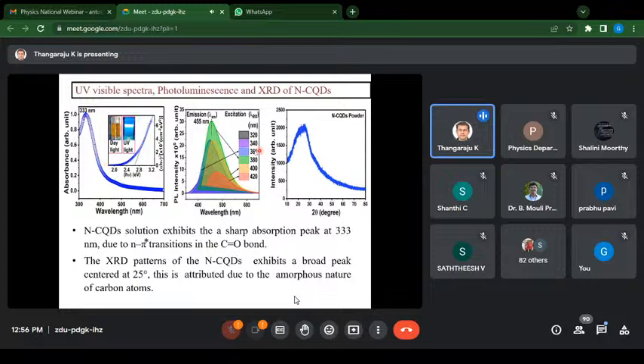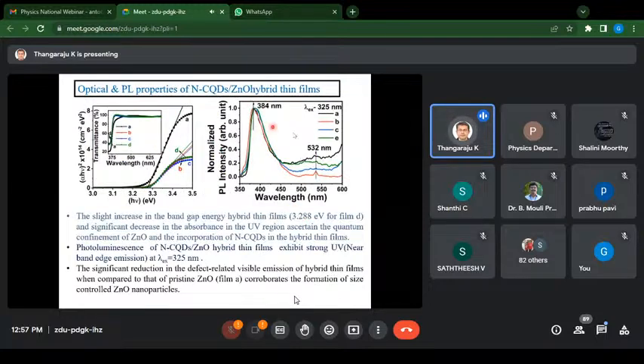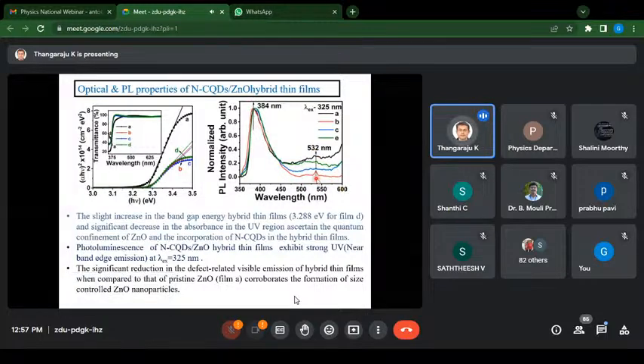around 333 nanometer, and the formation of carbon quantum dots is also confirmed by exposing to UV light. Under the UV light, it shows the blue light emission, which confirms the presence of the carbon quantum dots, and it is showing the typical excitation dependent PL characteristics. And we have made the hybrid structure, and the hybrid film is giving the band edge emission around 380 nanometer, and it is also showing the decreased defect emission of the zinc oxide. So this defect emission in the zinc oxide confirms the transfer of energy from the carbon quantum dots to the zinc oxide.